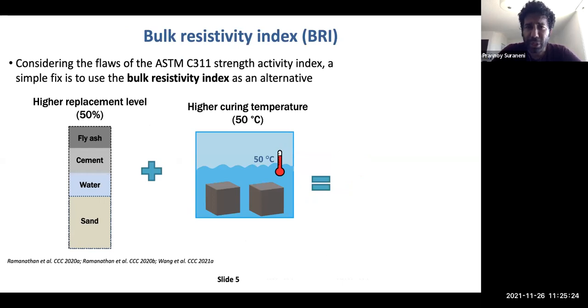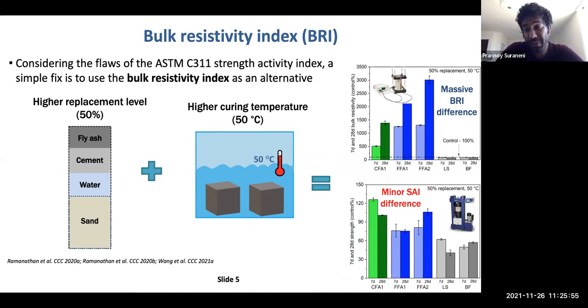So there are a lot of advantages in measuring bulk resistivity and standardizing it. Now, I mentioned earlier that the ASTM C311 or C618 strength activity index was flawed. So we actually propose a very simple fix for the strength activity index, which is essentially to use a bulk resistivity index. On the same mortars that you measure strength activity, you can measure the bulk resistivity as well. What we showed is that if you take a high replacement level, 50%, and a high curing temperature, 50 degrees, you will get some differences in strength activity between reactive and inert materials. They're about 20 to 30%. If you look here, these are the reactive materials, these are the inert materials, the difference is about 20%.